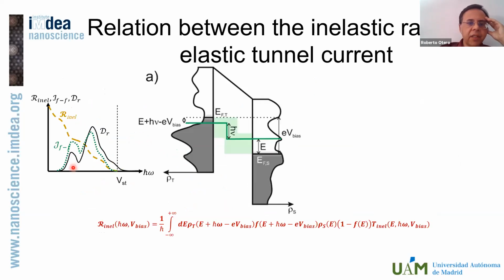Now, what we have in mind, therefore, is that we have some spectra that would be the true optical spectra, that there should be a role for the rate of possible inelastic transitions, and that the true spectra that we observe is somehow the product of those two factors. Now, how can we estimate the rate for inelastic transitions? Well, it should be proportional to how many occupied states you have in one electrode, right? So that should be the electronic density of states times the Fermi occupancy. It should be proportional to how many empty states you have on the other electrode. And that should be the density of electronic states at, say, the sample times 1 minus the Fermi occupancy. And there should be some weight for the probability for this kind of tunneling process to occur.